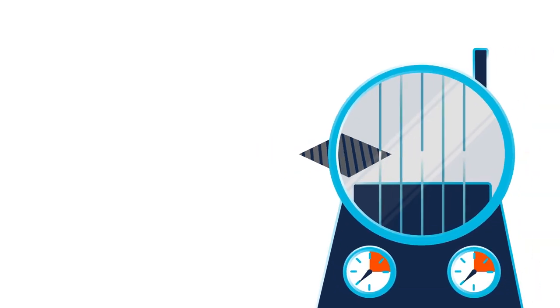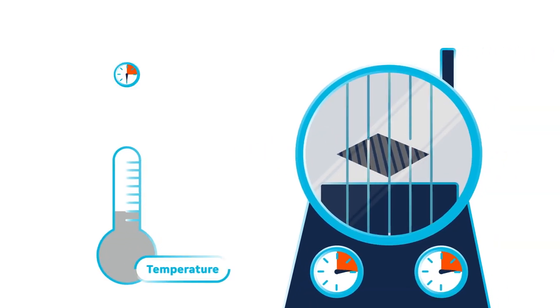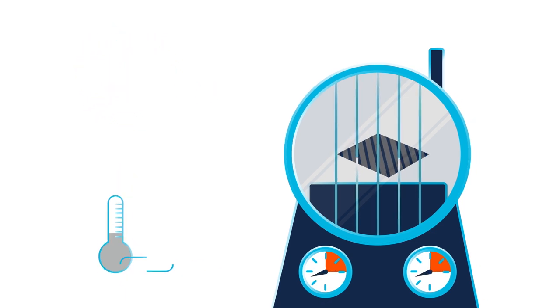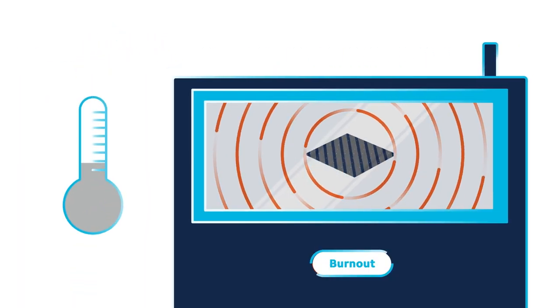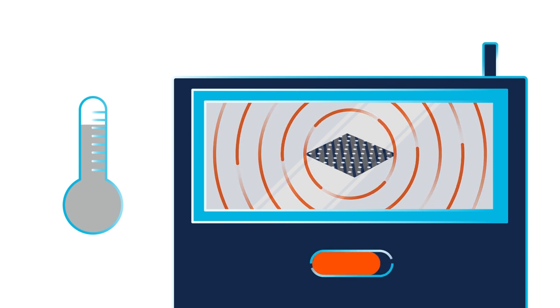Once all the plies are in place, the tool is put in an autoclave, where low heat and high pressure transitions the layered plies into a molded part. The part then goes through a burnout process to convert all remaining organic material to carbon.